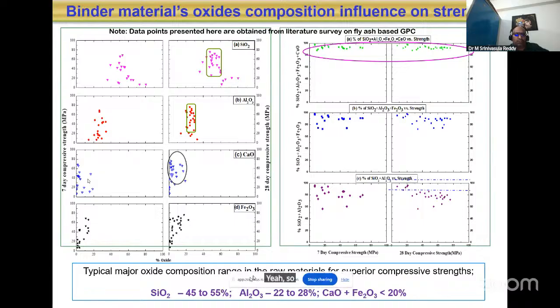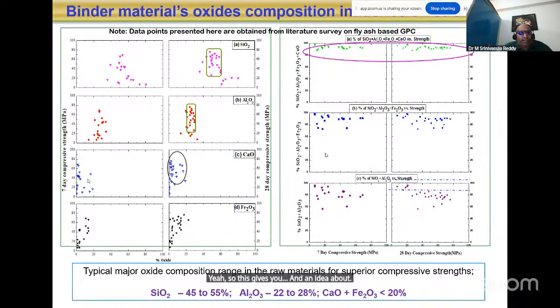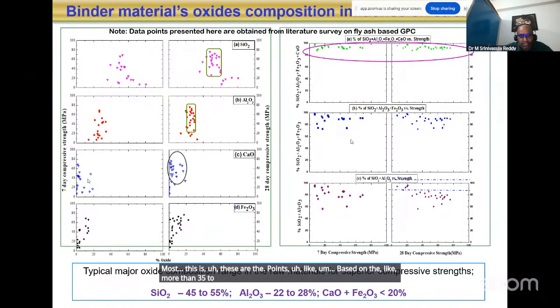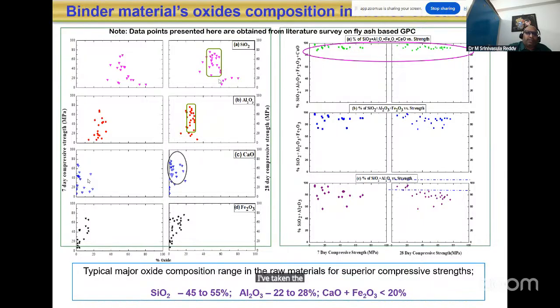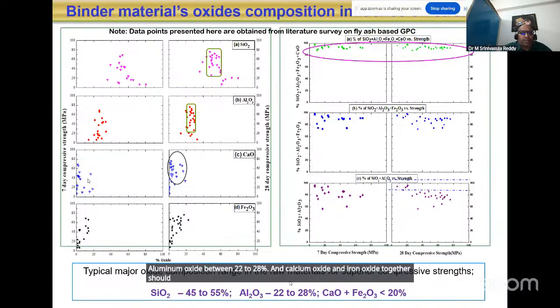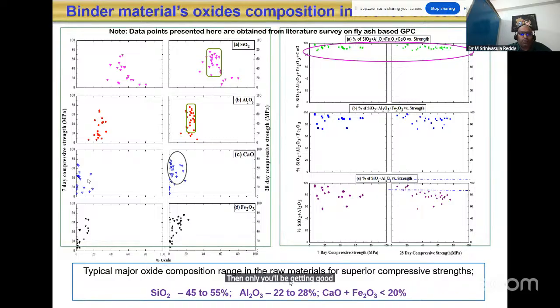Yeah. So this gives you an idea about the influence of various oxides on the final strength, like the 28-day strength or 7-day strength of the geopolymer concrete. These points are based on data taken from more than 35 to 40 research papers. Based on the data, what I found is the optimum composition that the waste should have to give better results is silica oxide between 45 to 55%, aluminum oxide between 22 to 28%, and calcium oxide and iron oxide together should be less than 20%. Only then will you get good geopolymer concrete strength.